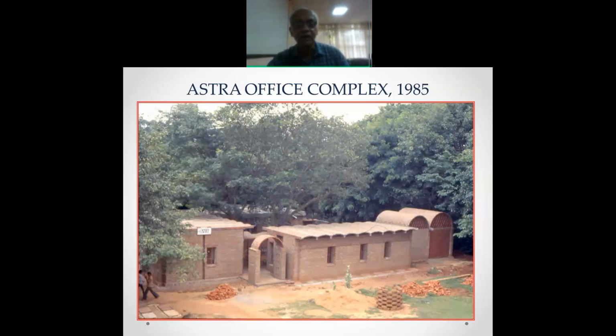And next year, we started noticing that some of the blocks were getting damaged, although we had used 6%. And at the corner, there used to be a crack. What happens is when you have excessive clay, the block will expand slightly when it rains, and it will contract when it dries. Alternately, when this happens, the corner develops a crack, and some of the surfaces will start peeling off. So then we started doing laboratory research, and we felt that you should not use a soil with more than 15% clay when you're using 6 or 7% cement. This had 30% clay. So this was the second learning we had. When you do experimental buildings, you come up with information which will help us.